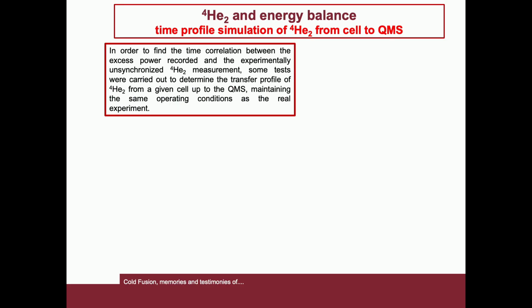Helium-4 and the energy balance, time profile simulation of helium-4 from the cell to the quadrupole mass spectrometer. In order to find a time correlation between the recorded excess power and the experimentally unsynchronized helium measurements, some tests were carried out to determine the helium transfer profile from a given cell to the mass spectrometer, maintaining the same operating conditions of the real experiment.